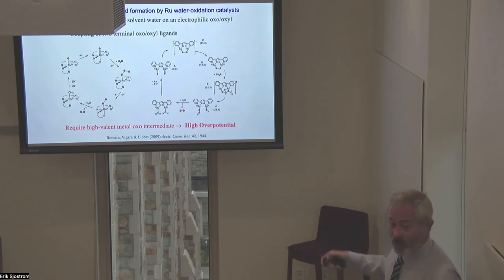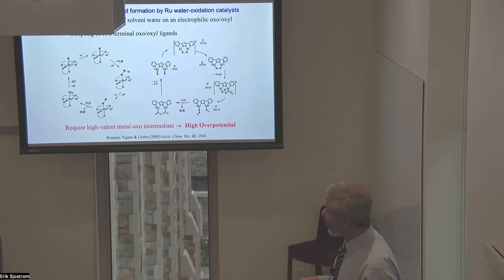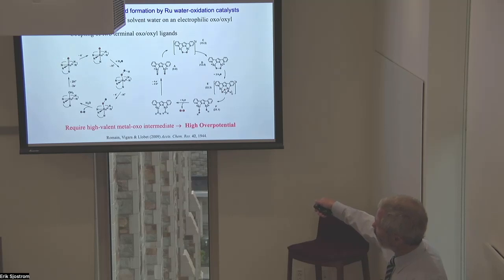One nice thing about ruthenium is that the bonds are very stable, strong bonds, and so you can label the oxygen of the ruthenium complex with an isotope, put it in water with a different isotope, and carry out a labeling experiment to determine where the oxygens came from. Did it come from the labeled oxygen, or did it come from the solvent? And these are two examples. One is referred to as a nucleophilic attack mechanism.